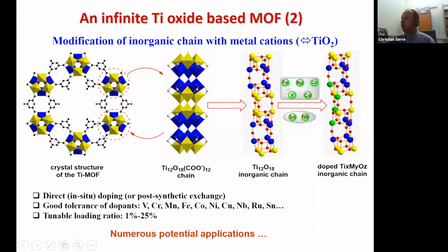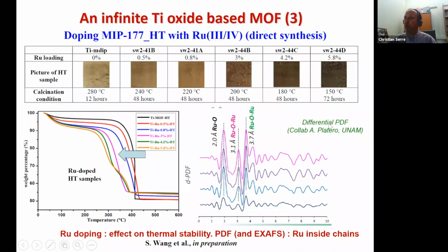For instance, transition metals like iron, but also ruthenium. And I will show you one example with the doping with ruthenium that we carried out in collaboration with Jorge Gascon, who is now at KAUST. When you introduce up to 5% or 6% of ruthenium in the sample, of course, the band gap decreases. You start to see a solid that is colored. And you see by TGA that the thermal stability decreases, probably because the ruthenium oxide, which is +3, +4 here, starts to be an oxidant and to degrade the ligand of the MOF itself when you heat too much.